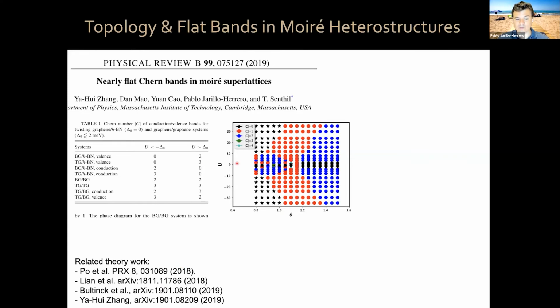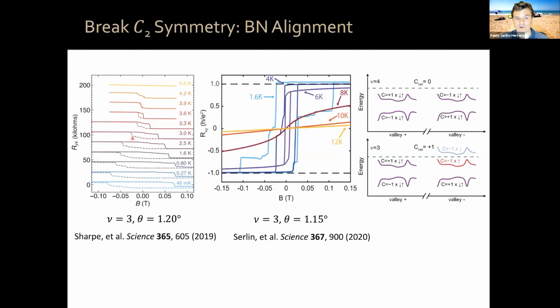Within a few months, the group of David Goldhaber-Gordon was able to realize the anomalous Hall effect in magic angle twisted bilayer graphene aligned to hBN. So you break the C2 symmetry because you have the hexagonal boron nitride, which breaks inversion symmetry, aligned to the twisted bilayer graphene.